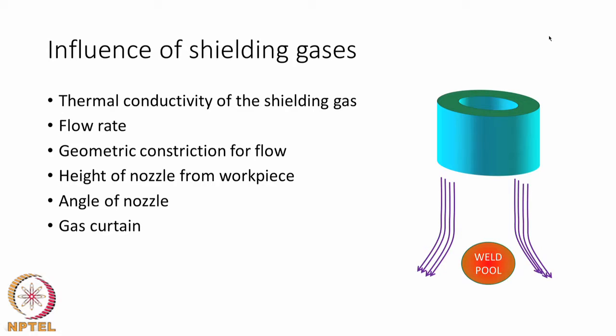So, there is also one more aspect that we need to keep in mind. What happens normally is, apart from the Gaussian nature of the heat source that is coming from the arc, we also have a situation where the shielding gas that is used plays a role with respect to the heat source distribution. So, I have shown here a toroidal space from where the gas is coming through, and at the center of the space is where the weld pool is located. To keep the schematic simple, I have not shown you the welding torch, which will be actually at the center of the toroid that I have shown. So, basically in the annular region, the gas is coming out and then going on around the weld pool, so that it is protecting the weld pool from contamination.